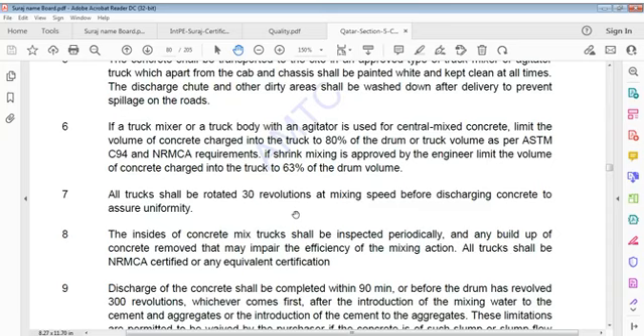If a truck mixer or a truck body with an agitator is used for central mixed concrete, limit volume of concrete charged into truck to 80% of truck volume per ASTM C94 and NRMCA requirements. If shrink mixing is approved by engineer, limit volume of concrete charged into truck to 63% of drum volume. A truck shall be rotated 30 revolutions at mixing speed before discharging concrete to assure uniformity.